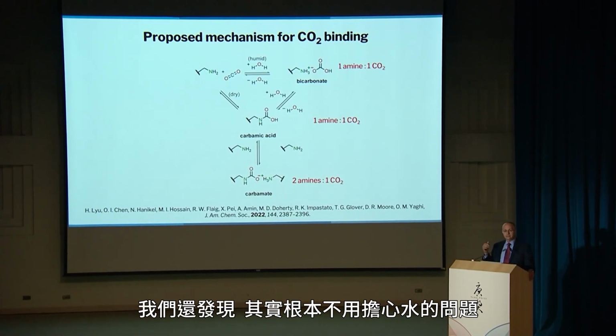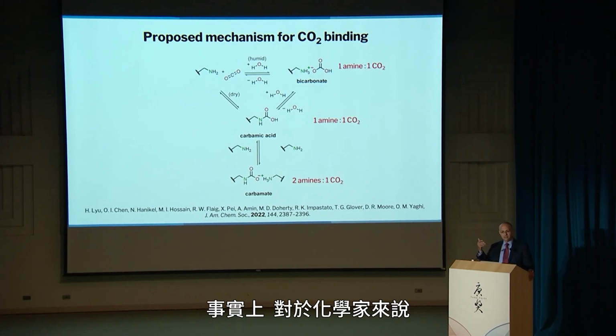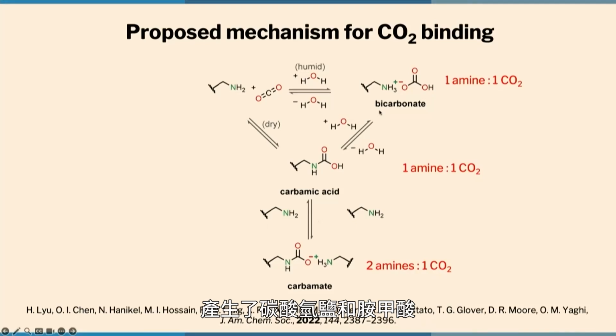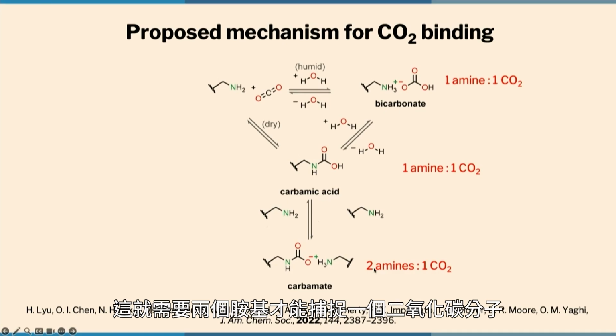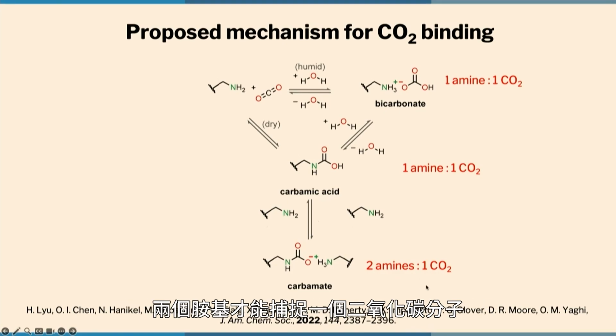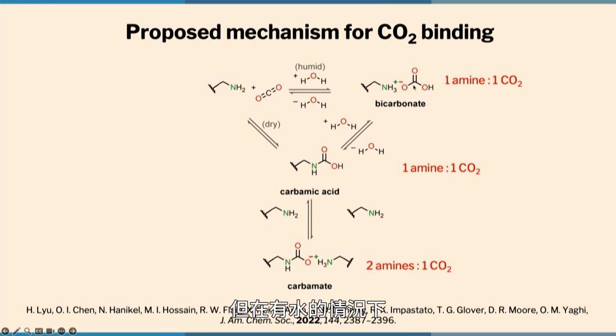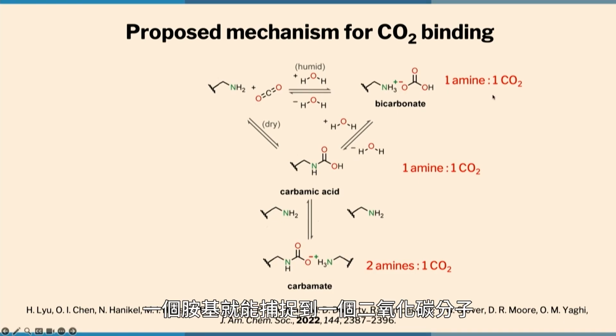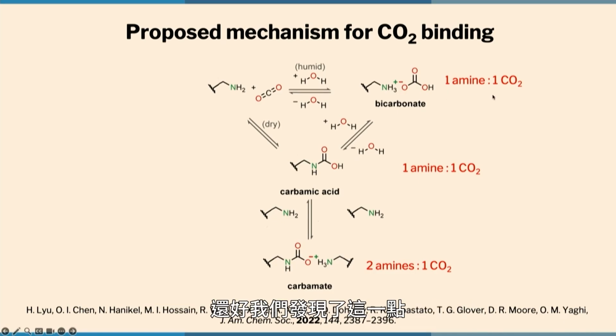We also found that, in fact, you don't need to avoid water. In fact, water, for chemists here, shifts the equilibrium towards bicarbonate and carbamic acid. If you don't have water, you will have carbamate, and carbamate requires 2 amines for each CO2. 2 amines capture 1 CO2. But in the presence of water, 1 amine captures 1 CO2. So this was a very fortunate discovery.